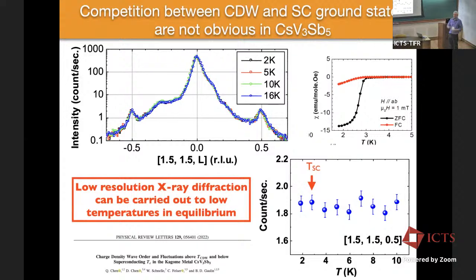And with regard to the linear dependence, you're correct to point out this very odd behavior, because most order parameters are curved, right? This eventually does come in flat at low temperatures, but you have to get to quite low temperatures compared to either the 94 Kelvin CDW long-range order onset, or the 150 Kelvin onset where we see the fluctuations. Nonetheless, it's very odd to see a linear regime that's that long. But what I was going to show you is that we've seen this before.